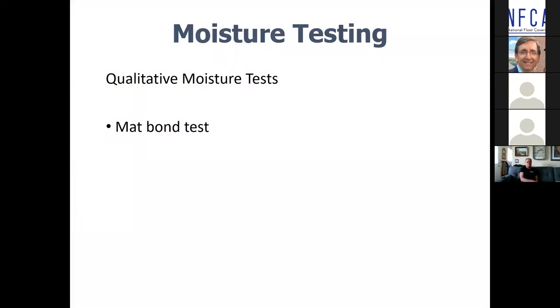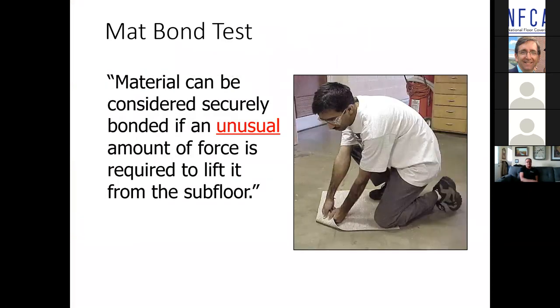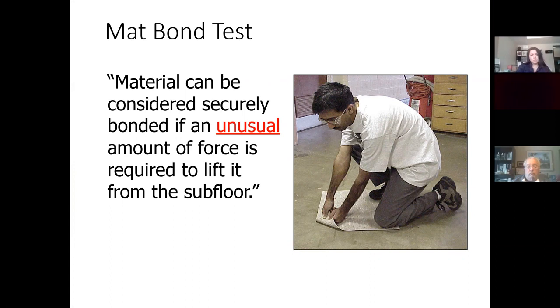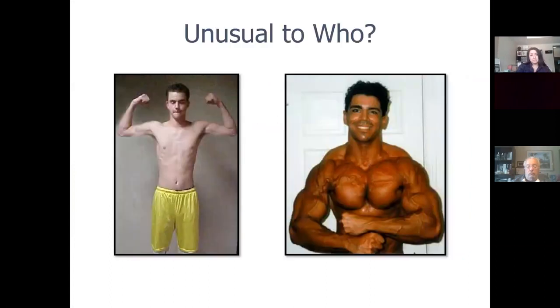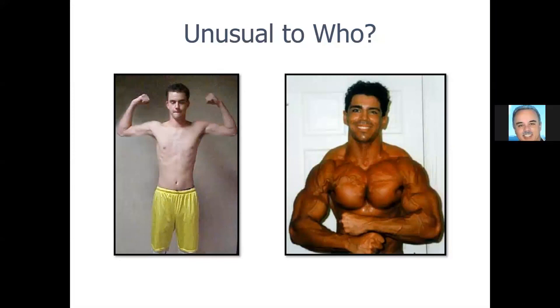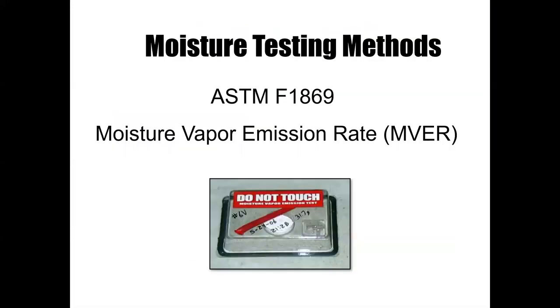All right. Still on the qualitative side, and we're actually at ASTM writing a new mat bond test, where it's basically a mock-up. You prepare the concrete exactly as you're going to prepare it for the full project: clean it, prep it, vacuum it, spread adhesive, put the flooring down, roll it, let it sit for usually a week, come back, and then see if an unusual amount of force is required to lift it from the subfloor. Well, unusual to who? There are ways of quantifying it that we use, but we'll see what the new standard comes up with. Let's talk about calcium chloride testing and why it's fallen out of favor.